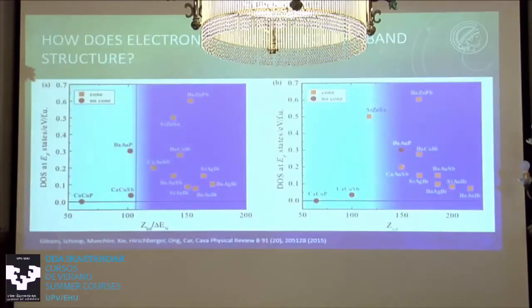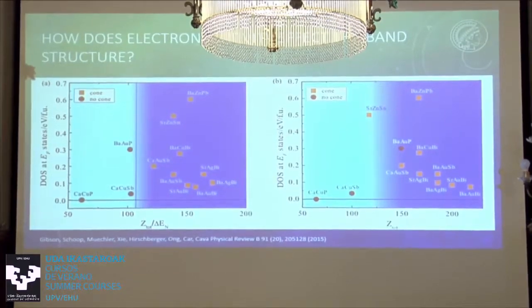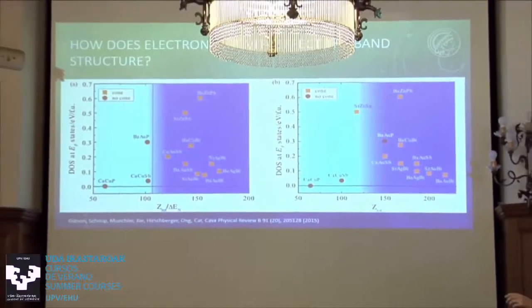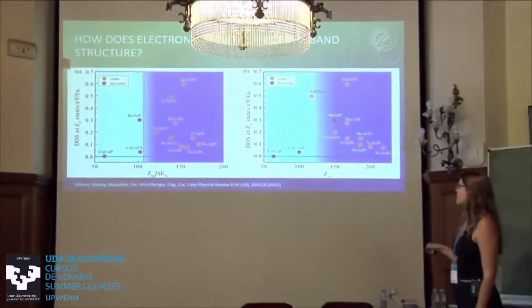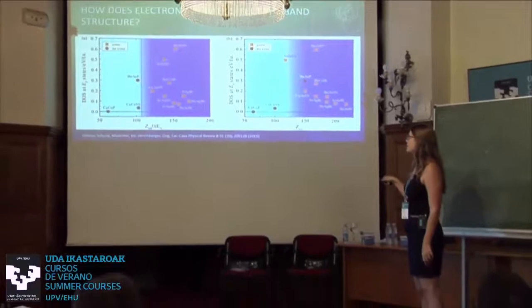And so then we made some plots. We calculated all those different band structures. We looked if there's a direct crossing or if it's not there. And we looked at how many other bands are crossing them. We quantified it by the amount of density of states at the Fermi level. So if there's a lot of other things interfering, or if there's not a lot, it's relatively clean. And so the density of states at the Fermi level is plotted on the y-axis here.